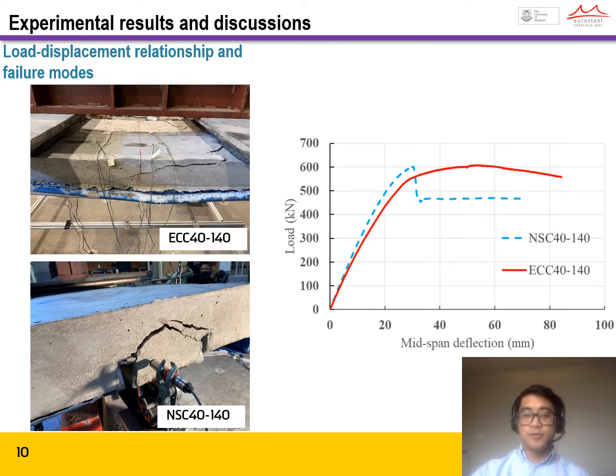For the ECC beam, the load increased linearly until 432 kN with a corresponding mid-span deflection of 20 mm, at which the high-strength steel beam started to yield. The stiffness of the beam then gradually reduced, and at a load of 546 kN, the first crack occurred near one of the loading points, and afterward the load increased slowly until it reached